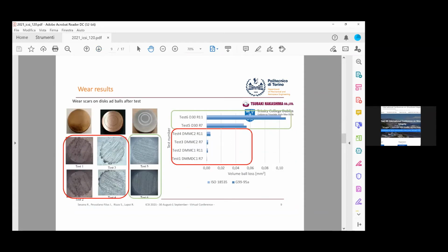As expected, values of sphere volume losses calculated with both standards were very similar. However, values of the disc volume loss calculated with the standard were found to be positive, thereby indicating a disc volume increment rather than a decrement. Such an output can be explained by referring to the significant roughness of the disc and the deposition of the debris in the surface irregularities, with the resulting conclusion that the formula proposed for the calculation of volume loss may not be reliable for the disc in this kind of experiment, where the abraded part is the ball, the pin.